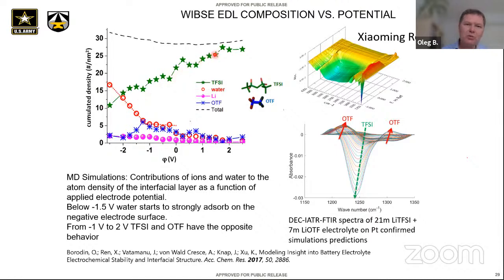TFSI is increasing as we go to high potentials. At positive potentials, triflate goes back. And I was very pleased when Xiaoming Ren at INL put together surface enhanced IR, and he did observe that indeed, as we go from high potential to low potential, the TFSI signal goes down and the triflate signal goes up. So at this limited range, he did observe that the selective electrosorption has been happening.